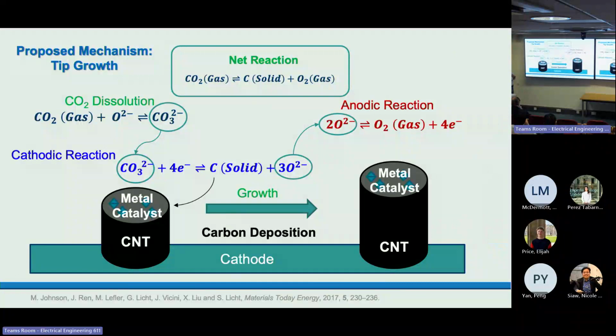So here is the proposed mechanism of the reaction. There are mainly two different types of mechanism proposed, and they are really similar to each other. One is called tip growth. The net reaction is the same for these two mechanisms. The CO2 gas will be split into carbon in the form of carbon nanotubes and also oxygen gas. Firstly, there is CO2 dissolution. CO2 will combine with one oxygen ion to form carbonate ions, and the carbonate ion will be transported to the cathode and be reduced to carbon in carbon nanotube form and to oxygen ions.